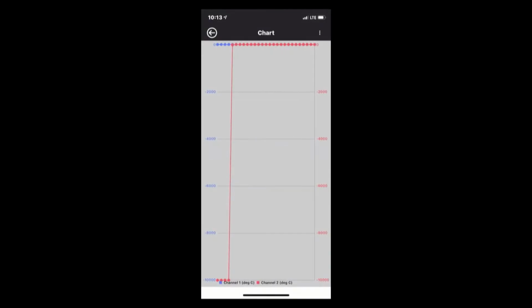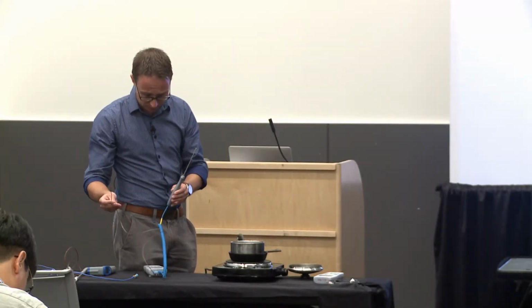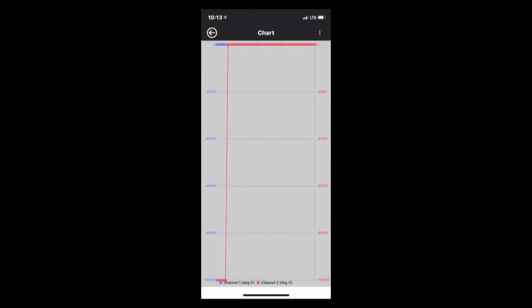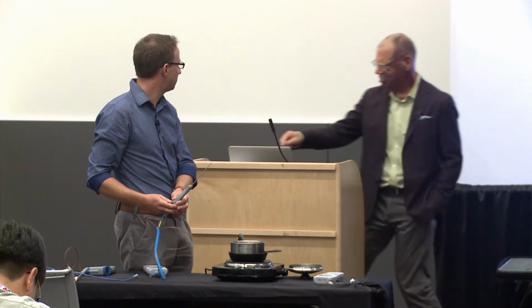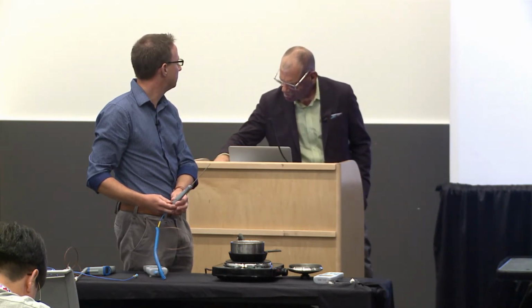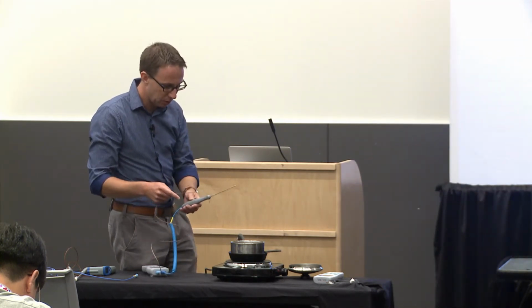So let's see here. Channel 1 is going to be our blue line, and in channel 1 I have connected an immersion probe, this is going to be an ungrounded tip with a sheath. Now in channel 2, I have a wire probe, and that's going to be an exposed thermocouple junction. You see the insulator and there's no sheath. I'm going to give this graph just a second to normalize. There you go. All right. So what I'm going to do is measure the temperature of this water, and we're going to watch the response rates.